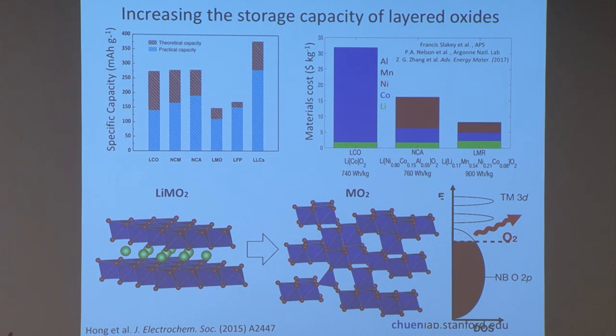On the top left, I'm showing you the theoretical capacity of many different types of material used for the cathodes of a lithium-ion battery, and also the practical capacity. So in blue is practical. So you can see the various chemistry, like lithium cobalt oxide, lithium nickel cobalt manganese oxide, and so forth. You're only using about 50 to 65% of what's available. And that is because I cannot remove all of the lithium in this material, otherwise the structure collapses and causes the rearrangement to occur.